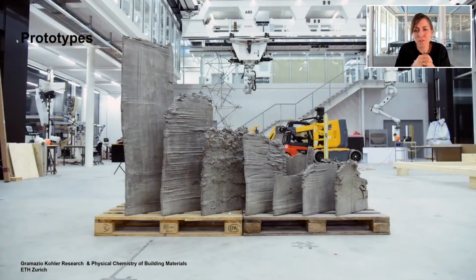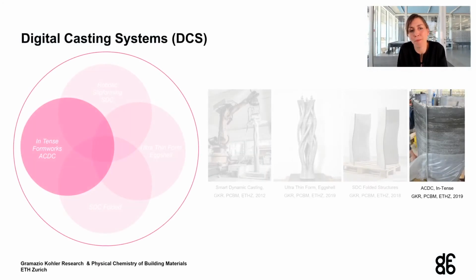In fact, the first prototypes turned out rather as failures, where significant ripples were shown as here in the picture. And this was caused by the increased friction of the formwork, which had an enlarged surface compared to the mullions, for instance. And also a very short processing time of the material that could be shaped due to the fast hydration. So Anna Szabo asked herself, how can I avoid friction? And that is how she came up with the idea of intense formworks.